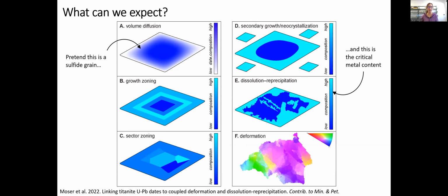So for example, if you look at A, if our critical metal is diffusing out of our sulfide grain, we'd expect some sort of diffuse gradual zonation, some gradual change in concentration like you see here. If you look instead at E, if our sulfide was partially dissolved by hydrothermal activity, and that material was then reprecipitated, but with a bit of a different composition, you'd expect some patterns like this. And finally, if we look at, say, F, and this is one I've adapted, if a sulfide grain experienced dislocation creep during deformation, it might show subgrains and internal distortion like this. And if our critical metal displayed a similar spatial pattern, we might then assume that it's affected by dislocation creep.